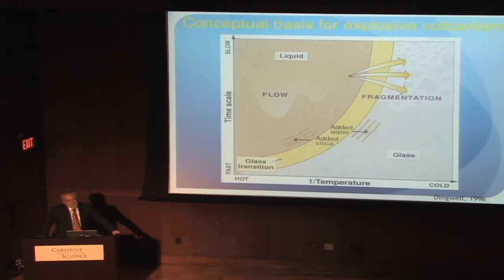For 5 years, 6 years, I can tell you exactly how long it takes to get something done in terms of a paradigm shift in geosciences. By 1995, all of the grandees of volcanology, who had done all that exquisite observational work over 30 or 40 years, which I had been somehow neglecting or skimming over with my generality, started to swing around hard to support our point of view. This was what we were talking about. This yellow line is nothing more than the glass transition. The glass transition is something that every Coke bottle has been through. It's something that every float glass window pane in this building has been through. And it's something that every explosive eruption on Earth has been through. In fact, it is the reason that the explosions take place.